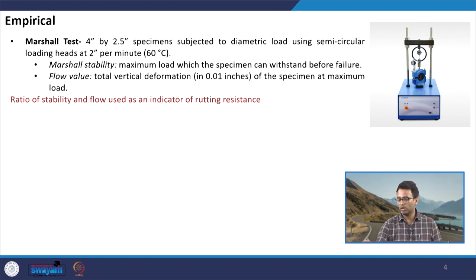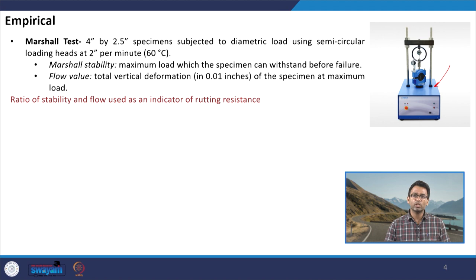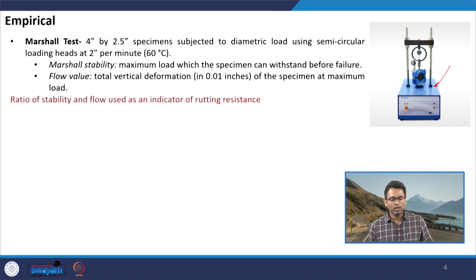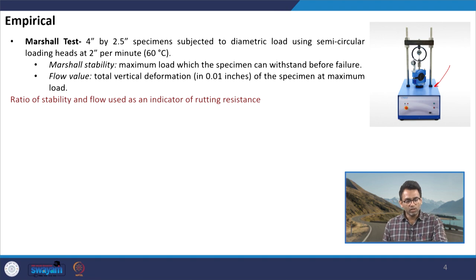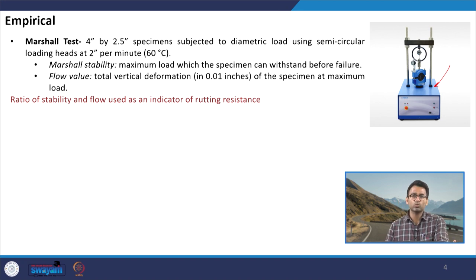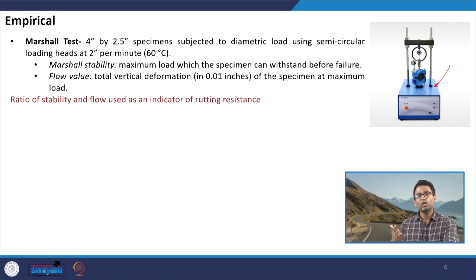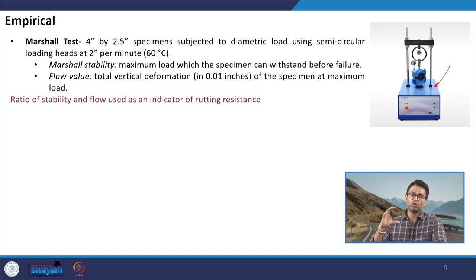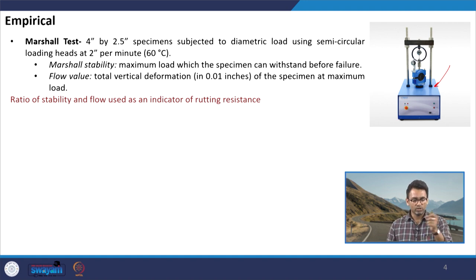A test carried out using a Marshall stability and flow machine — we prepare specimens that can be either 100 mm or 150 mm in diameter, with a standard height of either 63.5 mm or 90 mm plus. We load the material along the diametral plane and the test temperature is taken as 60 degrees Celsius. Using this machine we measure the Marshall stability value, which is the maximum load at which the specimen fails, and we also measure how much deformation or vertical movement has taken place — that is denoted as the flow value.